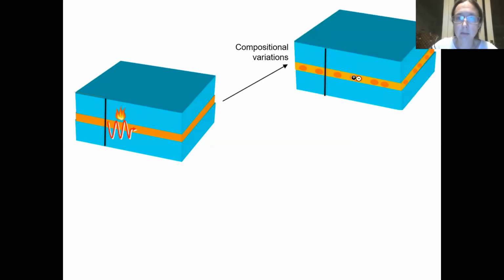Okay, so what we kind of expect then is that dislocations, these defects, will mess up the performance of the device. So that if we have an electron and hole in a quantum well that contains a defect, if they meet at the defect, we'll get heat out rather than light. Something must be stopping the defects from having this terrible effect on the light emission. And one suggestion for why gallium nitride LEDs work so well was that rather than this indium gallium nitride layer all having a lovely uniform composition of indium, that actually in some places it had loads of indium and in other places it had hardly any.